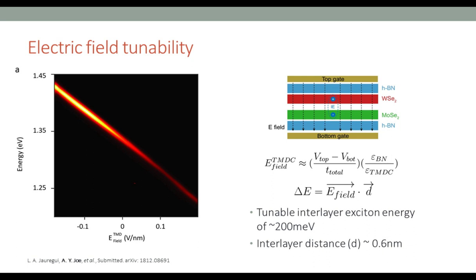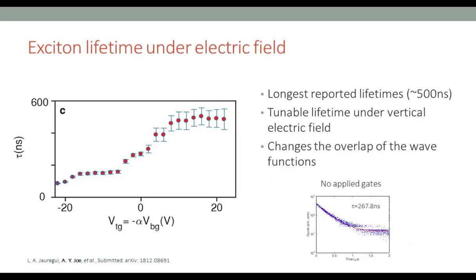So far we are seeing interlayer excitons, and they're widely tunable by electric field. Another measurement we can do is check the lifetime of these excitons, and we do this as a function of electric field. At 0 gate, we have around 280 nanoseconds, or 260 nanoseconds. This is already 2 orders of magnitude longer than the previous report. But what's quite interesting is that the electric field tunes the lifetime. By stretching the electron and hole wave functions, you can tune the lifetime from 100 to 600 nanoseconds. So this gives us some flexibility in terms of the lifetime.